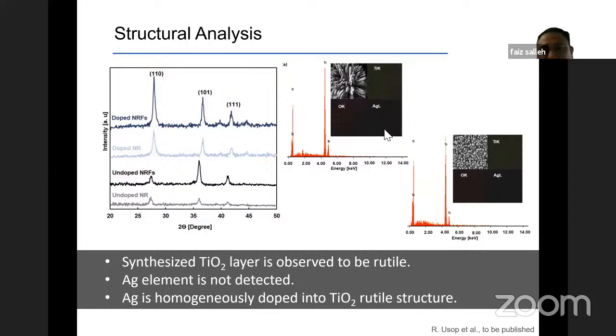Actually, we can hardly observe the distribution of argentum. Why? Because the weightage percentage that we put inside the chemical when we put the AgNO3 inside the process is quite low. It's below 1%.